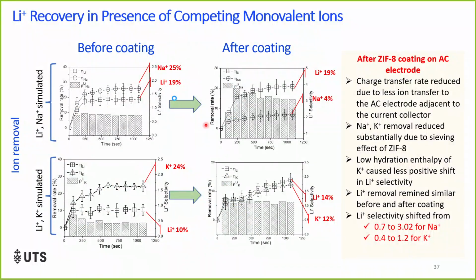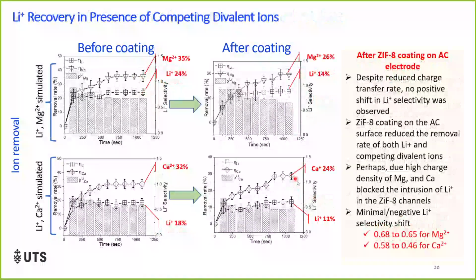So before coating and after coating, we compare the different lithium and sodium removal and the potassium. So we found overall the lithium selectivity shifted from 0.7 after coating, and we found 3 for sodium and 0.4 to 1.2 for potassium. So we have increased the overall selectivity of the lithium from this MCDI.